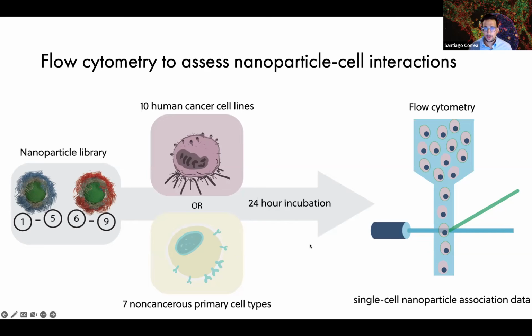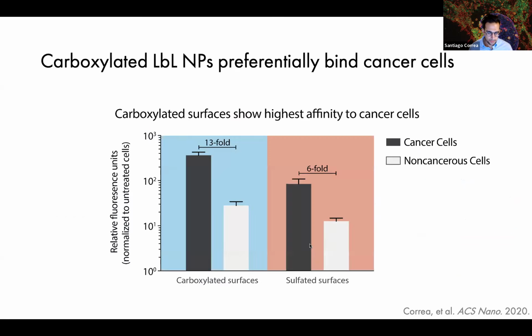After an incubation with these nanoparticles, we took these cells and analyzed them using flow cytometry to look at how much nanoparticle-associated fluorescence we could see in the different cell types. Looking at this from a very high level, instead of each individual formulation, I like to first show essentially the combined families. In blue here, we see all the formulations with carboxylated chemistries, and in red, we have all the formulations with sulfated chemistries. In this dark gray bar, we see how many carboxylated nanoparticles are binding to cancer cells, as opposed to healthy cells in this white bar.